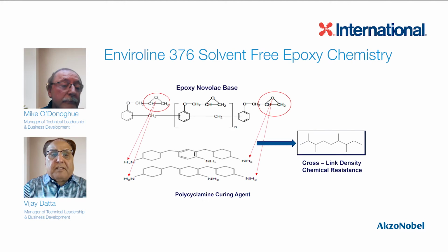This is epoxy resin. Mike, you mentioned the oxygen and the hydrogen. That's what we do. We really try to open up this triangle there. When it opens up, it gives you the polymer chain as well as produces hydroxyls, which gives you very good adhesion to the steel.